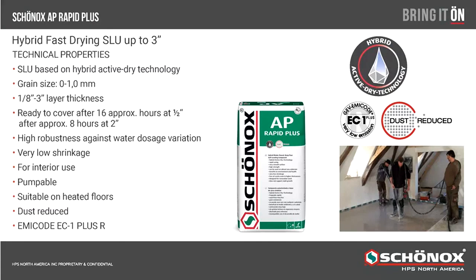AP Rapid Plus, we are looking at a product that we can go to deeper applications. The self-leveling can go up to 3 inches. From 1/8 to 3 inches is normally what we're looking at with AP Rapid Plus. This is eliminating that process in multifamily installations where they are actually removing the existing gypsum systems and then installing plywood and doing a patch around it. That is a very risky maneuver, not only for our risk management, but for the health and safety of our occupants. So this product can actually be installed up to that 3 inches to infill those areas that we need to infill on our multifamily applications. So we're ready for floor covering with this product in 16 hours at 1/2 inch and approximately 8 hours at 2 inches.